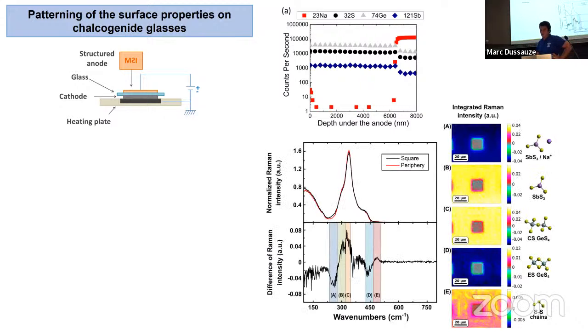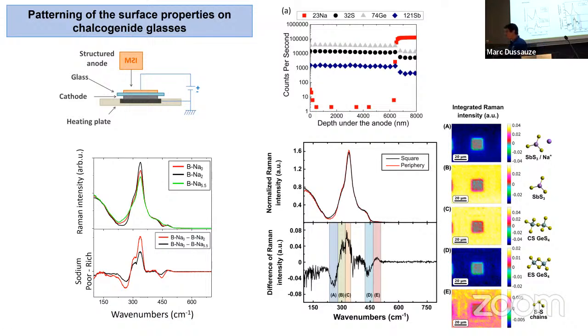And then we try to look at the glass structure. So we use this imprinting method and we do some Raman measurements. And we compare here the very tiny changes in structure that we observe by doing this Raman difference spectra to the first ones that I have shown you just before. Just before, these spectral changes were obtained by going to the melt. So you start from the melt, you quench it, and you obtain this different structure. Here, the change of structure is obtained at 170, 200 degrees. So it's far away from the melting temperature. And all this is obtained just by moving the ions inside the glass.